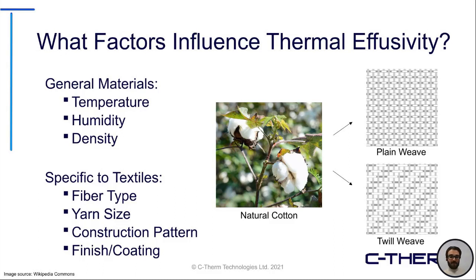Now, density is really dependent on the material that you're testing. You can imagine a lofty, down-filled jacket would obviously be much less dense than a plain sheet of fabric. So there are differences in density that will influence the overall measurement, but also the density that you're essentially imparting on the sample, meaning how much you're compressing the sample. If you recall, there was the image of the compression test accessory, the CTA device, which can be used to apply varying force loads on top of your sample material. For any samples that are compressible in nature, like most textiles and fabrics are, the extent to which you're compressing those samples will have an influence on your measurement.